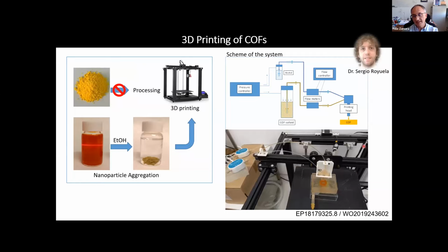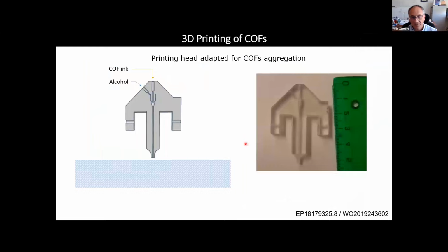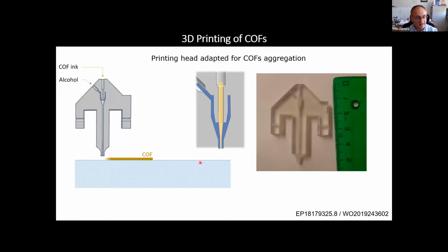And we set up this experiment. Here we have a microfluidic controller. This is a microfluidic reactor. And this is a 3D printer that we modified. We changed the tip of the 3D printer, and instead of the typical tip, we put our microfluidic reactor. This is the microfluidic reactor that we designed. This is the COF colloid, going through the central channel, and we incorporate the alcohol in the other channel. The idea was that if we incorporate the alcohol, we will produce the aggregation of the COF, and if we move the tip of the 3D printer at the same time, we can probably print our COF.